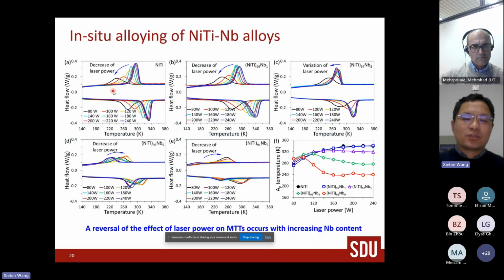But there are also factors that suppress martensite transformation. For example, the dissolved niobium atoms in the matrix will cause severe lattice distortion, and this kind of lattice distortion will suppress martensite transformation, and this effect will increase with the increase of niobium addition. So with lower niobium addition, the factor that increases transformation temperature is the key factor, and with higher niobium addition, the factor that suppresses martensite transformation is the key factor. So the transformation temperature changes a lot with the increase of niobium addition.